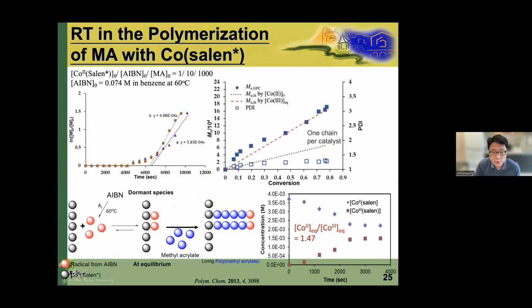are trapped by cobalt-2. But due to the different equilibrium constant, not all cobalt-2 was converted to organocobalt-3. Only part of the cobalt-2 converted to organocobalt-3, and it reached the equilibrium. So since it has reached the equilibrium, it will not trap the radical anymore and start the polymerization. So in this case, the theoretical molecular weight should be calculated based on one organocobalt-3 per chain, not all